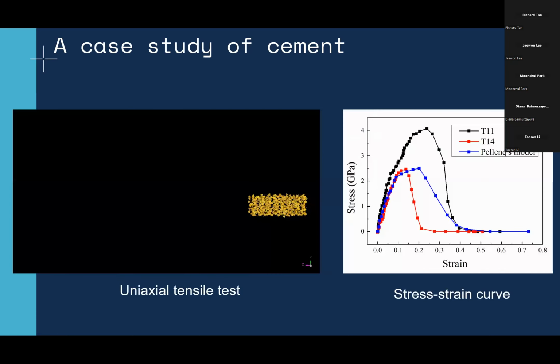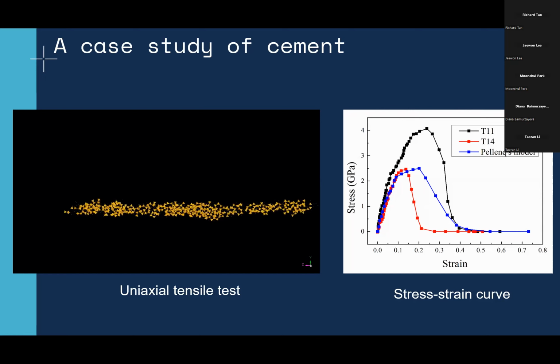So here on the left side is the trajectory of one structure under tensile simulation. As you can see, it shows that the structure fails due to the shear stress and follows a 45 degree angle of the cross section. Also, in the stress-strain curve, it demonstrates a different fracture behavior.